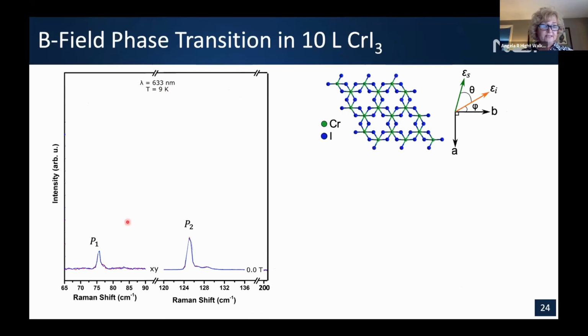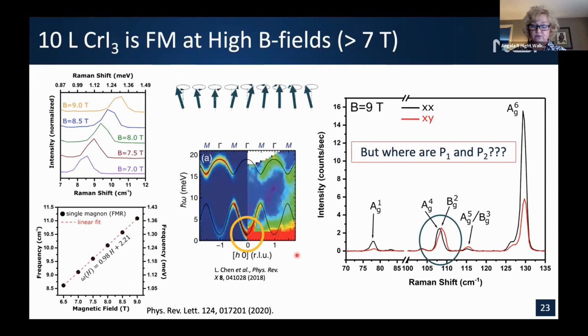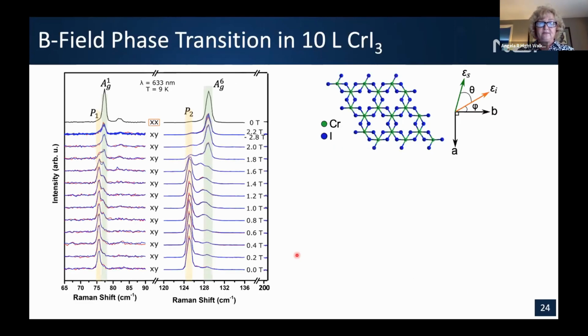So what I'm showing here is a Raman shift along X, and I'm highlighting these two features, the P1 and the P2. We're going to start at 0 Tesla in the XY, or the cross configuration, and we're going to increase the magnetic field. And this very top feature is in parallel at 0 field. And what you can see is a dramatic shift of the spectral weight in the P1 and the P2. That weight is getting shifted back to the expected phonons. So we were quite surprised by that.